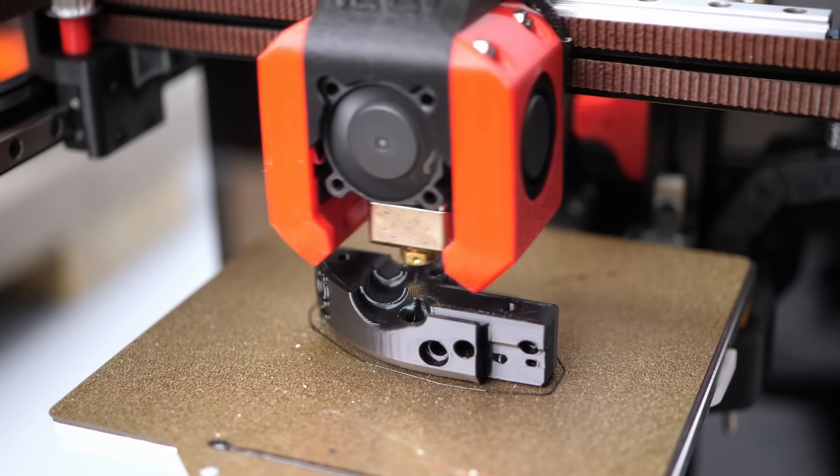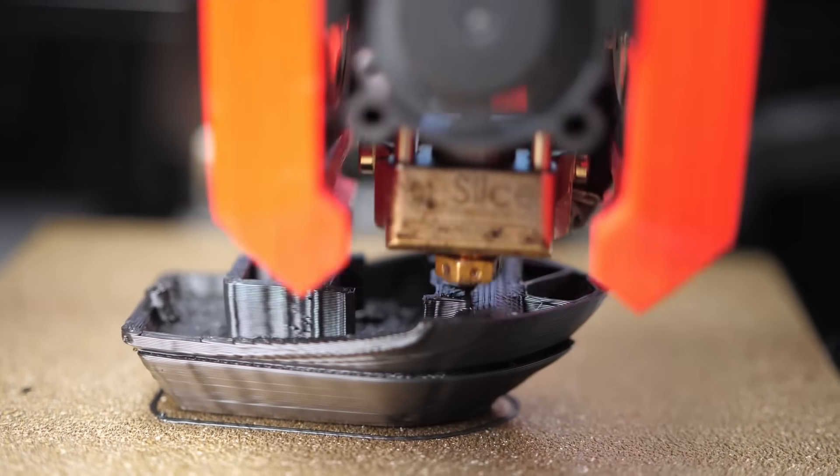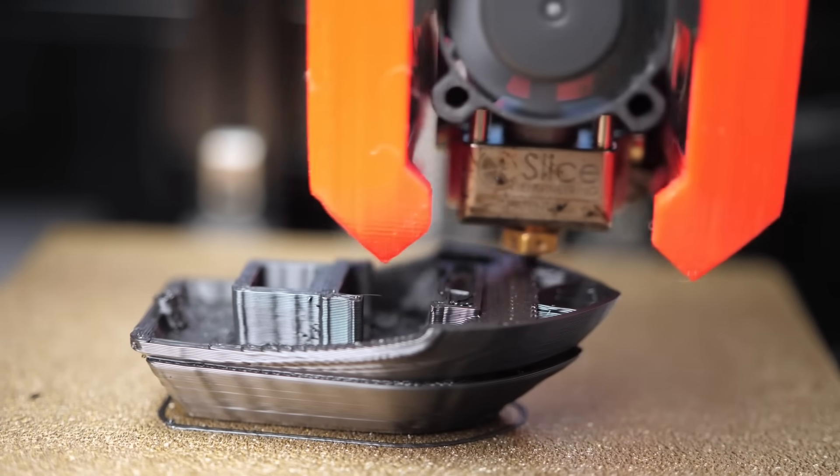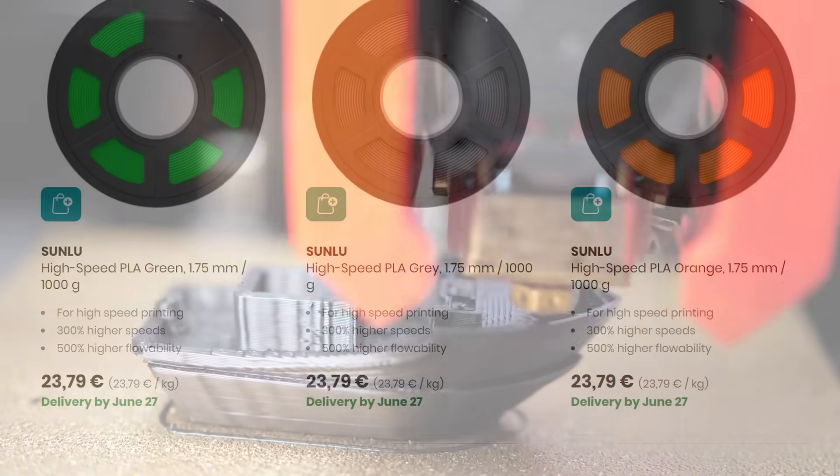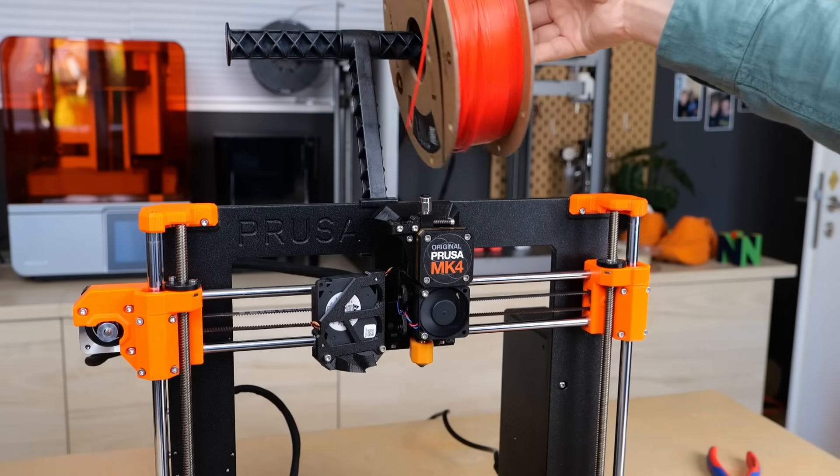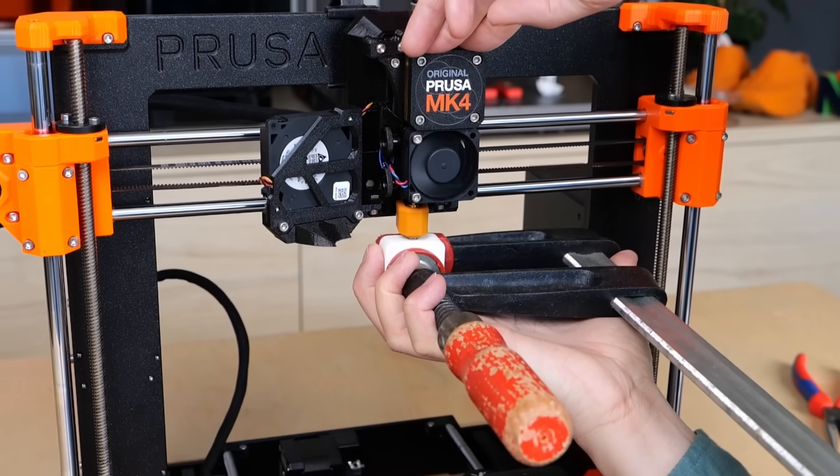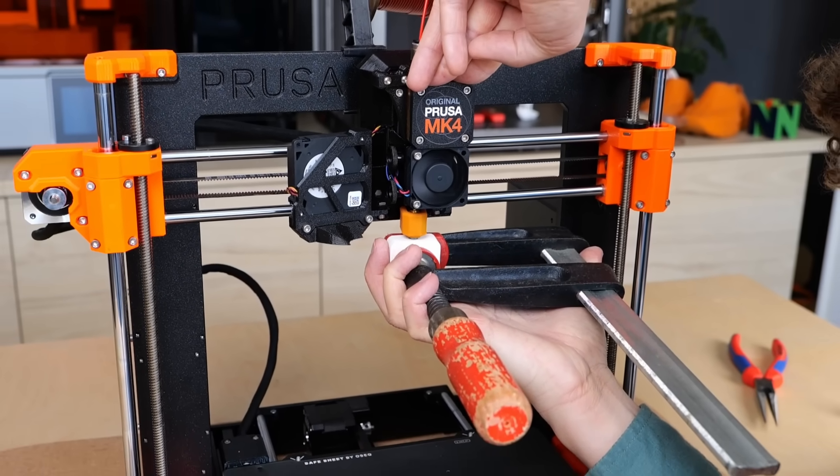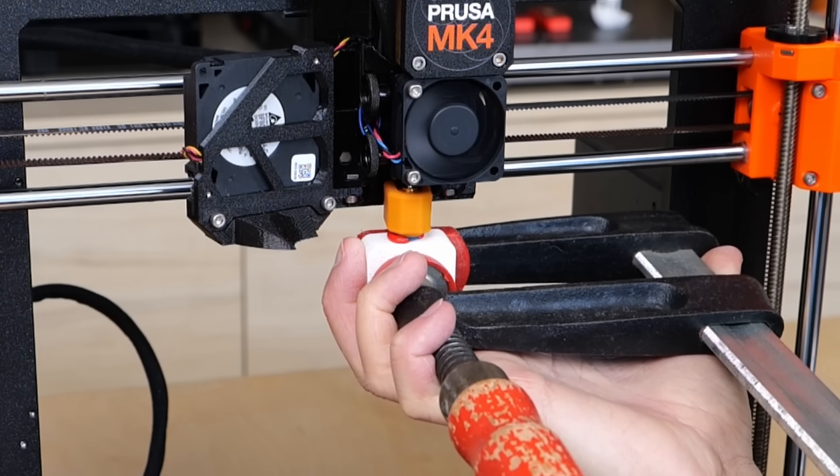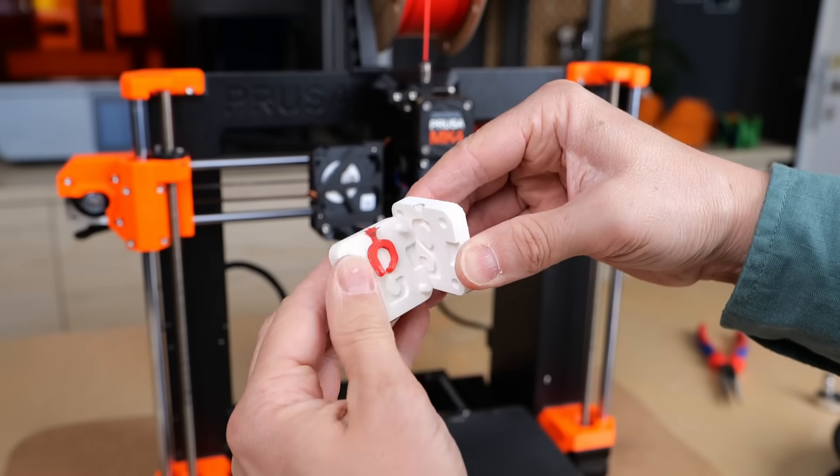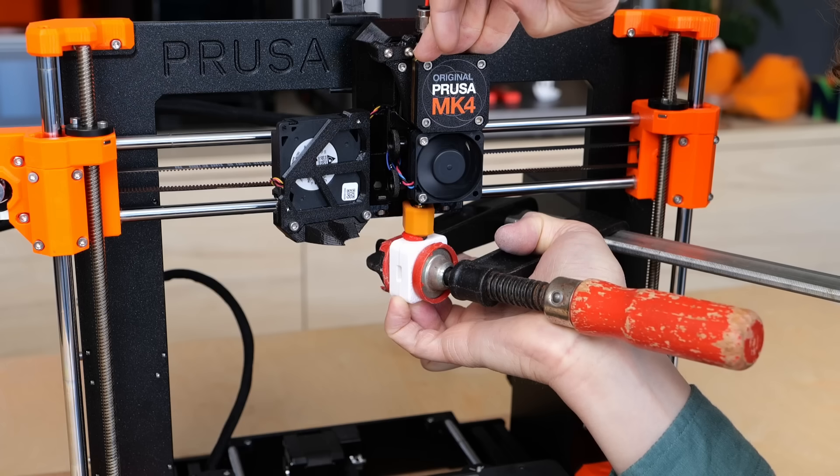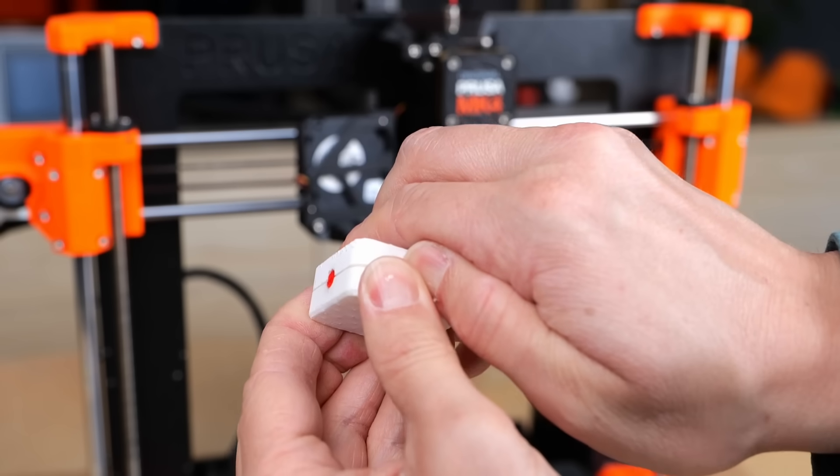When you want to 3D print really fast, you not only need a hotend that can melt all of the plastic, but at some point the small nozzle orifice becomes so restrictive that it gets hard to push the rather thick plastic through it. Yet we have seen more and more high-speed materials coming to the market recently trying to solve this problem. That's why I loaded Polymaker's Polysonic PLA into the Prusa and gave it another try. There was again material coming out of the sprue, but the result was another step forward with around 40% of the mold filled.